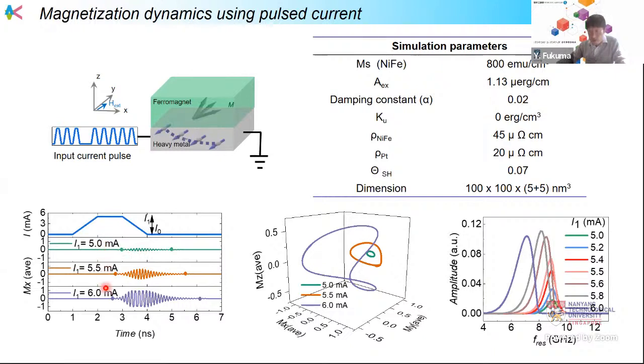When we increase the current, we can see a large precession like this. Then this is the trajectory of the magnetization. In the case of a small current, we can see this kind of small precession. But when we increase the current, this kind of trajectory is strongly modified. If the trajectory is drastically changed, then the effective magnetization decreases. That's why we can see the decrease of the resonance frequency in the spectrum.